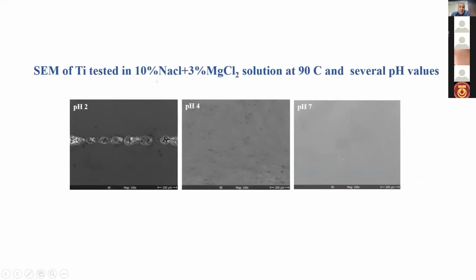The scanning electron microscope indicates that for the sample tested at pH 7 and pH 4, there are no defects, there are no pits, but in contrast at pH 2 crevice corrosion appeared at the surface of the titanium alloys after decreasing the pH to this value.